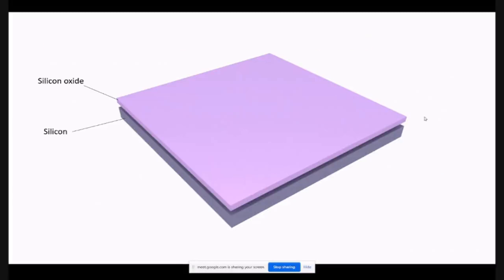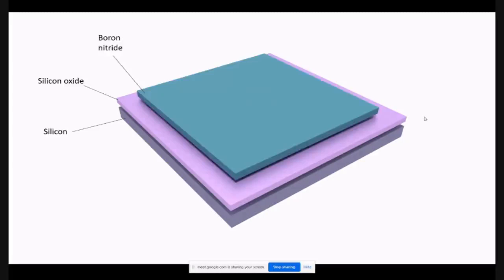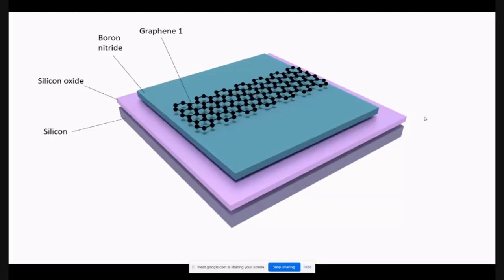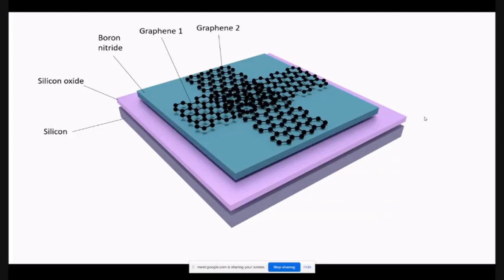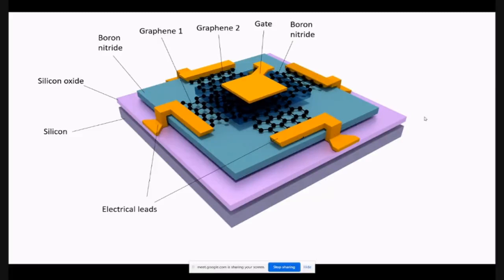However, if you want to measure it across the two layers, I just took that example to show you how the Seebeck coefficient is analyzed in this context. But now the question is that we will put one graphene on top of the other and measure the potential across the two. So you start with silicon and silicon oxide. You put a boron nitride layer because this is a nice environment for the graphene. Then you put a layer of graphene. Then you put another layer of graphene across so that you can put electrical contacts wherever you want. And then put another layer of boron nitride to cover it, to make a nice, clean, high mobility region. And then you put your gates and electrical contacts.